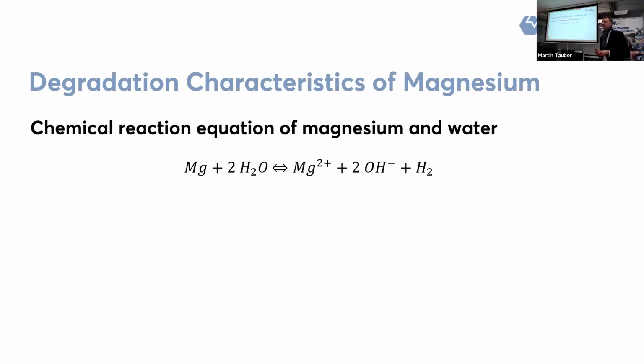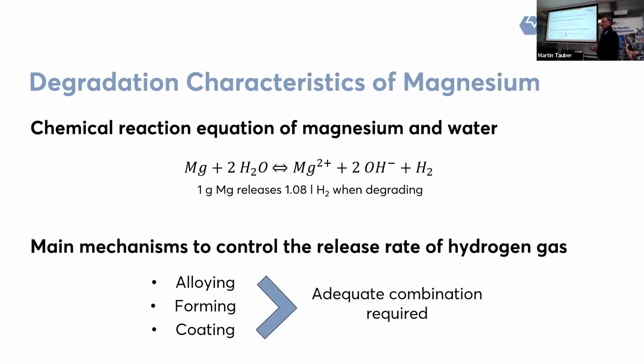This hydrogen release can create some headaches when you develop magnesium implants, because there's always 1 liter of hydrogen released when 1 gram of magnesium degrades. And that's not something you can change. The only thing you can do is define the period in which the hydrogen is released over time. And this is something you really need to control. Typical mechanisms to control the release rate are finding suitable alloys, finding a suitable forming process, and last but not least, applying a coating if you want to. So in the end, what we are looking for is a very nice combination of all 3 of these parameter sets to create an adequate base material which can be used for biomedical applications.